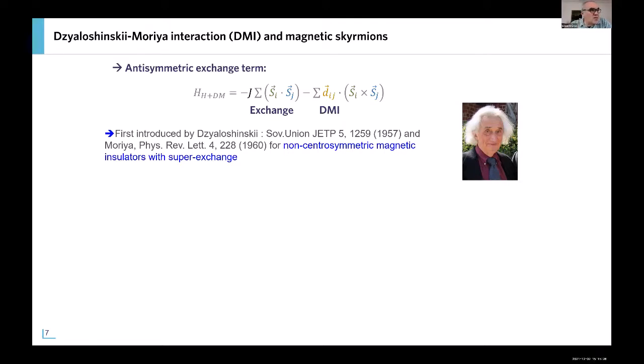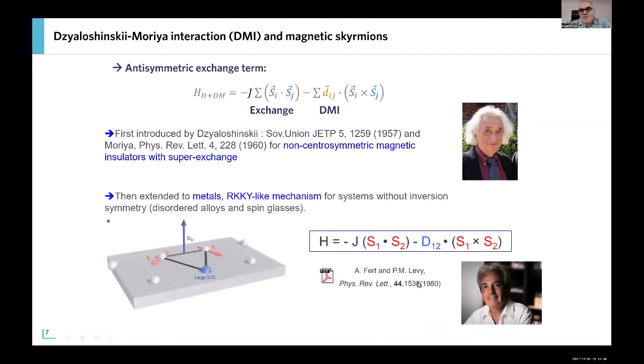And for quite a long time, it was supposed that this antisymmetric exchange interaction would be important only for these magnetic insulating materials. In fact, Albert Fert, together with Professor Levy, extended this to metals at the beginning of the 80s, using for the description the RKKY, so the indirect exchange interaction mechanism in spin glasses, in order to explain spin glasses that contain heavy metal impurities. The electronic interaction between neighboring spins can occur when going through this impurity with large spin-orbit coupling. Basically, it can be described by also adding to the Hamiltonian a term that has exactly the same form as the Dzyaloshinskii-Moriya term for the bulk materials.